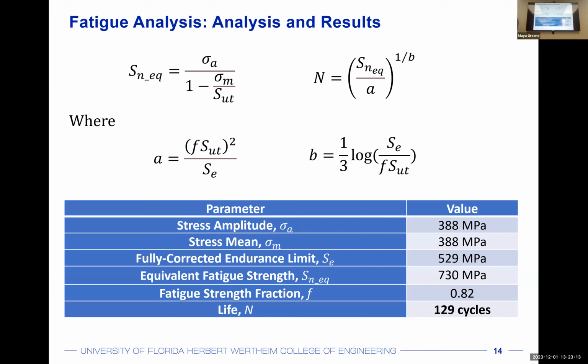You would get cycles incredibly low, but for the very small dust, you could get cycles just incredibly high. So this went for something on sort of the average case that we might expect to see from larger size boulders that might impact the structure. And 129 cycles was deemed acceptable in this case, again, based on the statistics related to the size of the regolith that we would actually expect to impact the lander.